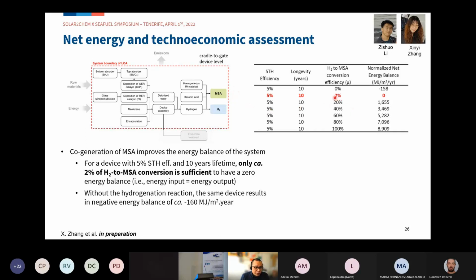However, if we just introduce a little bit of hydrogen-to-MSA conversion, just 2%, we can actually achieve a net energy balance of zero. And of course, as we increase this hydrogen-to-MSA conversion efficiency, which we already demonstrated in the previous slide, we can achieve a more positive and much more favorable net energy balance.